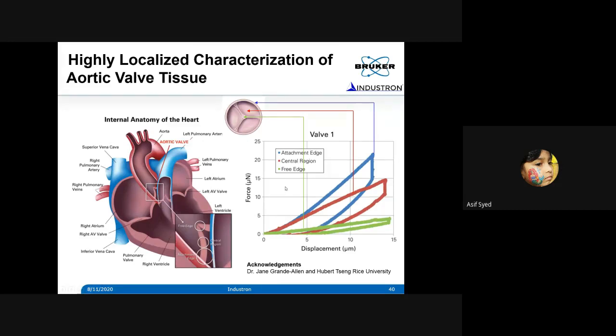This is what I'm showing in this particular slide. In this wall, there are three different regions. This is the edge of the region which attaches to the cell, the blue one. This is the mid region where you will have most pressure; it has to withstand the pressure of the blood pumping. And this is the end region, where it is a free edge. It has to be very elastic, because when you're closing, it should conform to the surface so the blood doesn't leak. So at three different regions, you need different properties. You have a gradient in properties.